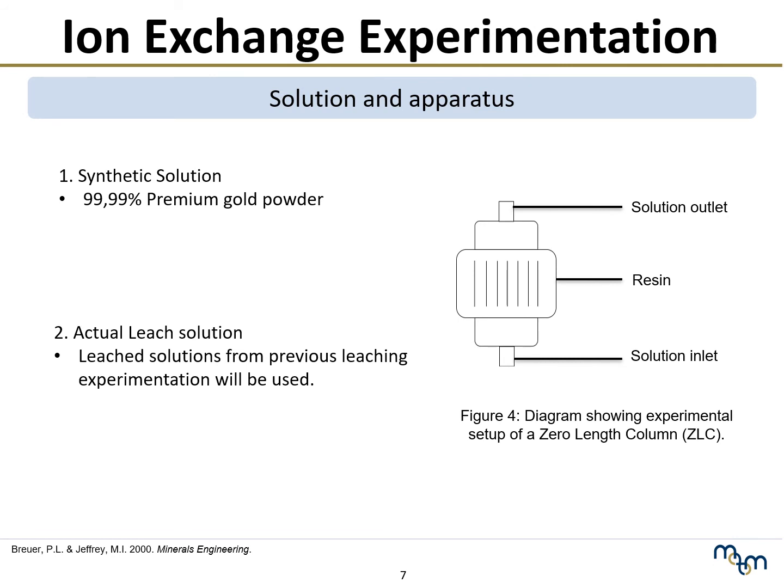Subsequent to the leaching process is the ion exchange method. This utilizes resins in order to remove the aurothiosulfate ion from the solution by attaching onto the resin. Initial tests utilize the standardized leach solutions, and these serve to validate the ion exchange process in thiosulfate systems, as well as to measure the resin capacity without the interference of contaminants otherwise expected from actual PCB leachate. The tests are then repeated using actual PCB leachate.